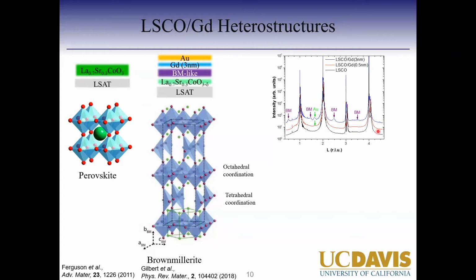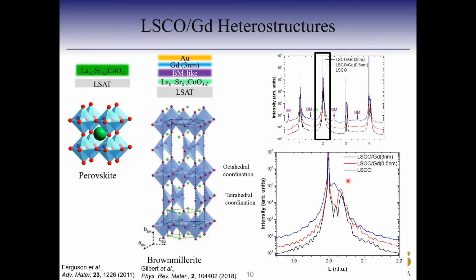So this is an X-ray diffraction study done at SSRL, where they looked at gadolinium half, gadolinium 3, and just an as-grown system. And you can start to see that for gadolinium 3, because you're quadrupling your unit cell, you start to see half-order brownmillerite peaks present in the structure. And if I zoom in to this particular Bragg peak, you can even see for gadolinium half, the system is actually different.